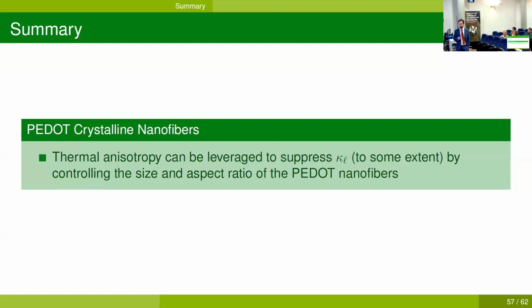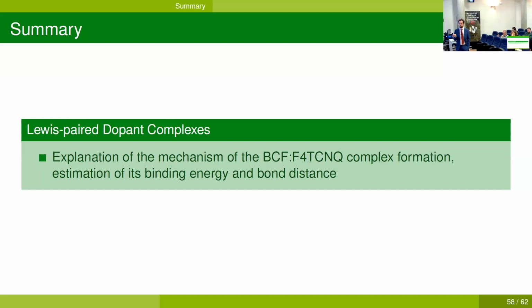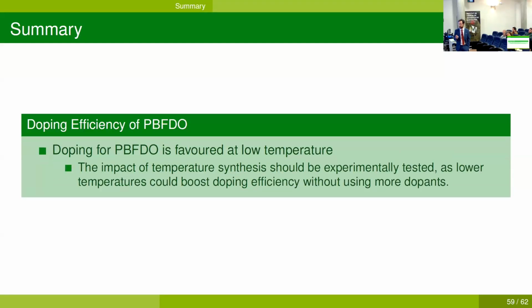We have also talked about PEDOT crystalline nanofibers. We have seen that thermal anisotropy can be leveraged to a certain extent to suppress kappa L if we are able to control the size and the aspect ratio of the PEDOT nanofibers. We have tried to explain the mechanism of BCF-F4TCNQ complex formation and the Lewis pair doping approach. And we have estimated its binding energy and bonding distance.